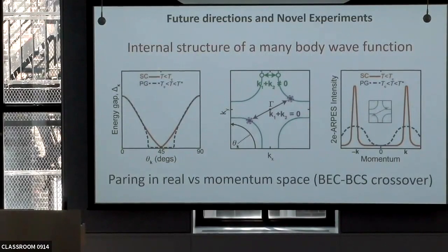If the pseudogap was made of preformed pairs, you could imagine that you would have a much broader distribution, perhaps peaked around the same points, but without coherence. So really, this would be the kind of scenario which I would like to see. If instead there was no gap and none of that, you probably would see a completely uniform distribution of intensity. And so ideally, the experiment one could dream of is to do a coincidence experiment, see a situation of this kind, then come in with a pump, drive the system, let's say quench superconductivity, and see that this signal disappears. So the coincidence signal disappears, and then see what remains, whether this remains or just a completely flat angular response remains. So that to me would be the way to probe the pairing in a system.